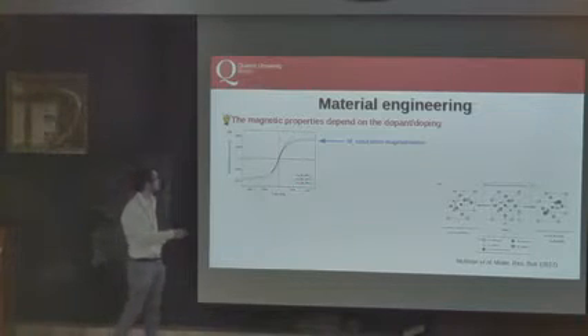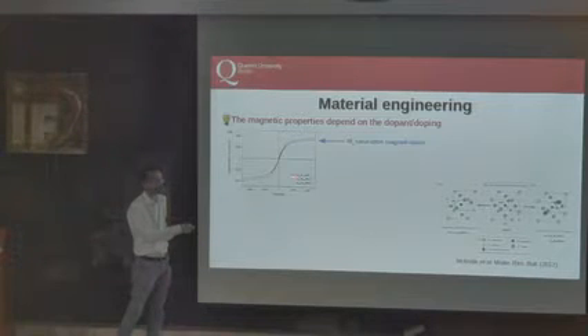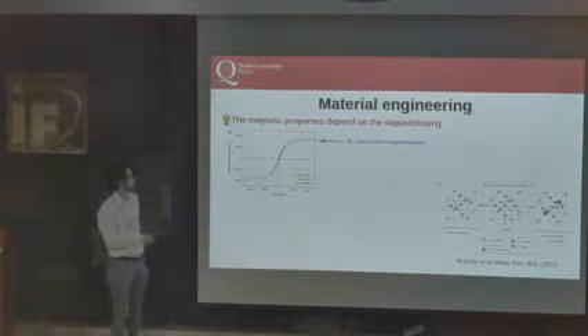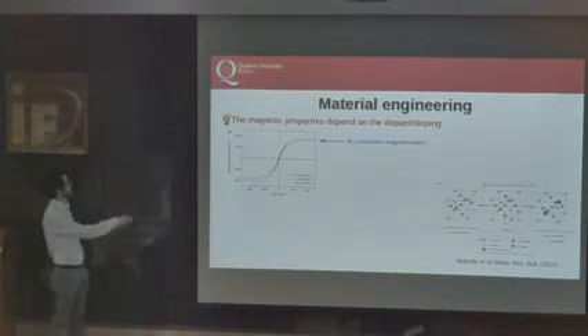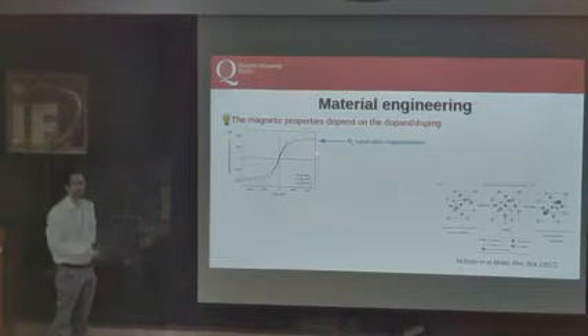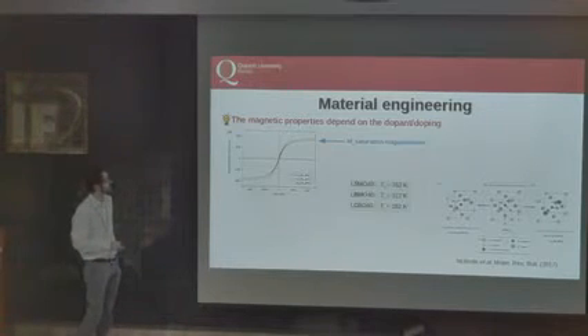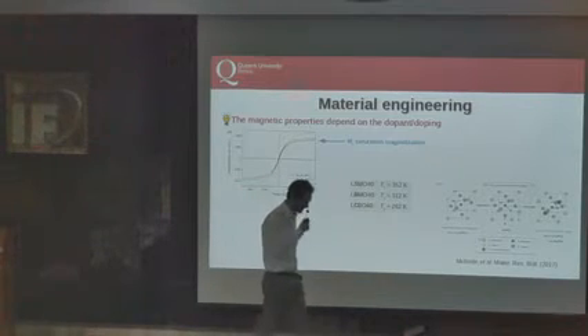I hope you can see, there are three compounds. This is lanthanum strontium manganese oxide, this is doped with barium, and this is doped with calcium. As you can see, the saturation magnetization, the maximum magnetization that you can achieve, depends on the dopant. What also depends on the dopant, and we're clearly interested in this value, is the Curie temperature. This time in Kelvin. So for instance, if I dope with calcium, you see that it will switch probably too early. Barium is okay at room temperature, but it's probably also switched too early. The LSMO, as I said, has a high enough Curie temperature. This is why we focus the attention on the compound doped with strontium.